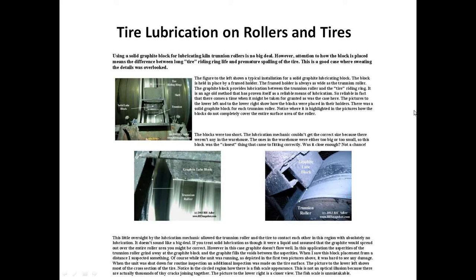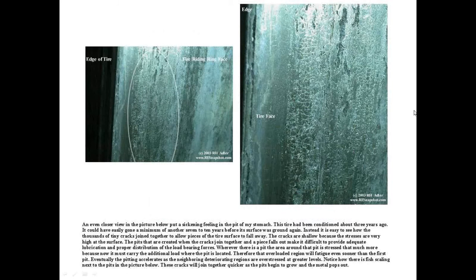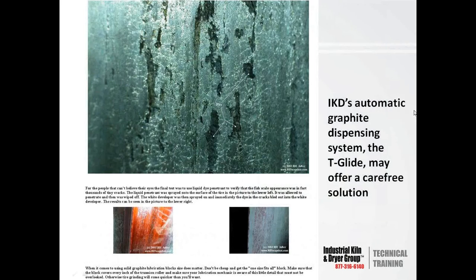Okay, we're going to run through these slides a little quickly because we're running out of time, and lubrication is more of a whole side issue in itself. But lubricating tires and rollers is always important to retard the wear that you have. If you look at the face of a tire and roller, you get a lot of microscopic spalling, pitting, and so forth if you don't have proper lubrication, which is generally graphite. Right. So it shows the same thing.